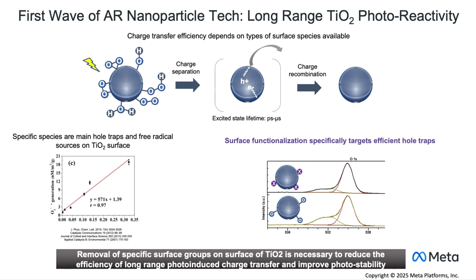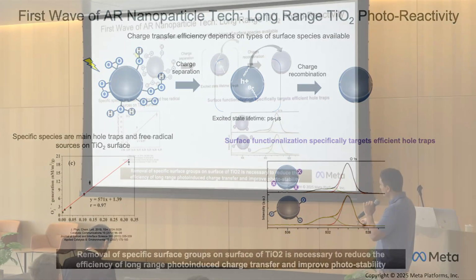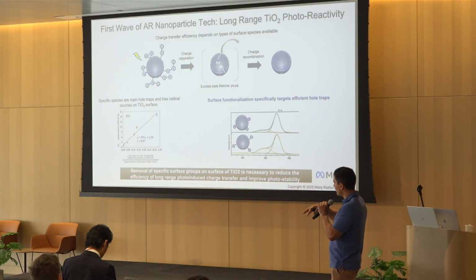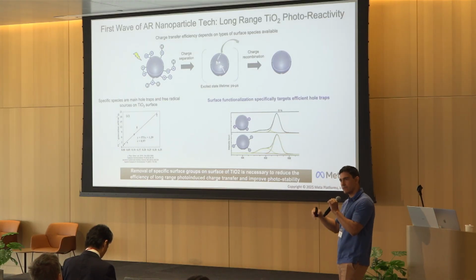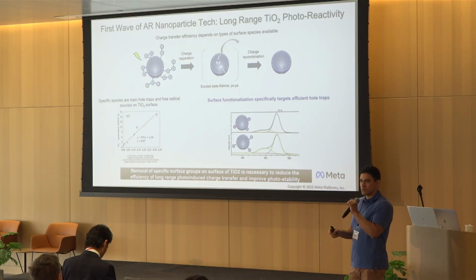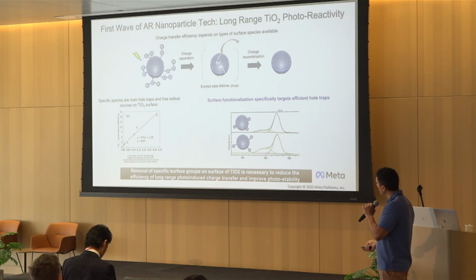So we always had a trickle of photoreactivity, and the real breakthrough here came from understanding that the surface of these nanoparticles, the oxide surface, is a very complex chemistry, has lots of different species and defect types, and each defect has a very different type of excited state lifetime. So that lifetime is the window of opportunity that we have to collect the charge on the surface and then transfer it to the environment. So what we did here is just identify which surface states were the culprit for most of the photoreactivity, and then we devised chemical treatments to specifically target those surface species and make a much more photostable nanoparticle.